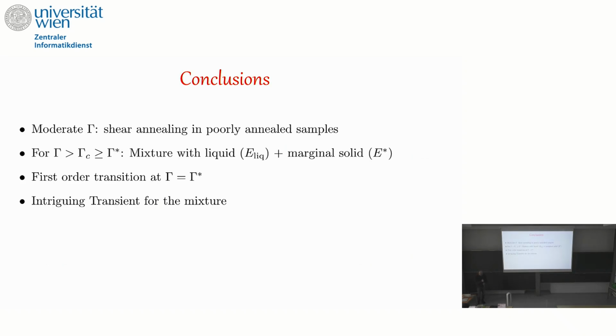We have some ideas. To conclude, what we show is that in general, when you do this quasi-static protocol, it is non-intuitive, but it should shear anneal the sample. From a disorder point of view, it's very clear what is going on. You are removing the shallow parabolas, but I think it would be nice to see this in an experiment, that the system becomes more fragile. At a certain point, you arrive at a solid that cannot sustain being solid anymore, so it develops a fracture, it develops a shear band. Then, depending on the initial condition, you have an intriguing transient, because if you are already a marginal solid, it just diffuses. If you are not a marginal solid, then you will see the shear band first transform the solid into the marginal solid, and then it starts to diffuse.